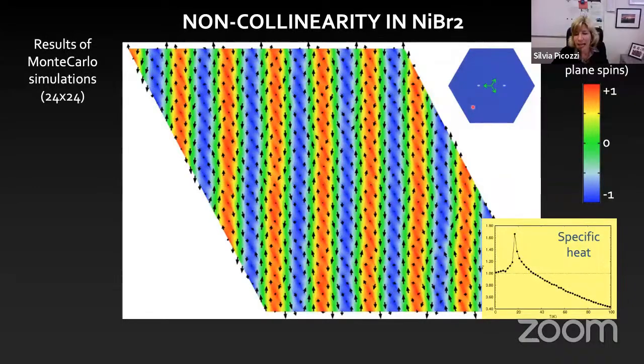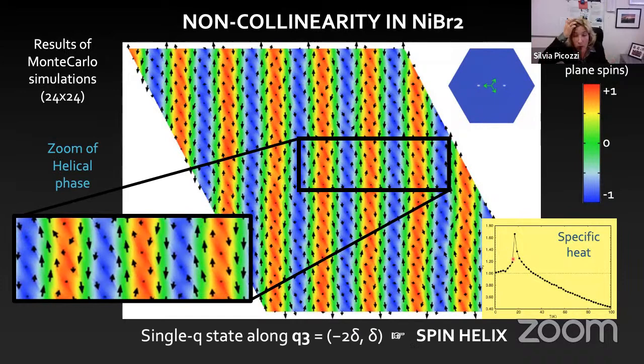A wave. And also by means of Monte Carlo, you can estimate the specific heat and extract the Curie temperature. And you see that they are low. This also we expect. Frustrated systems generally have low ordering temperatures because they need to satisfy many interactions. So we expected that, and it's also compatible with what people measured for bulk systems. So it's of the order of 10 or 20 Kelvin. And so this we expect, right? We have frustration in the system, and we know a spin helix is likely.